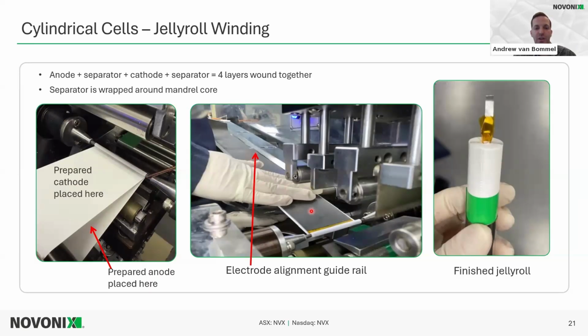This is just showing the cathode placed on the top with an electrode alignment guide shown there, so everything is aligned. Again, the same thing, the anode has an overhang of 1 millimeter on each side, and the separator further has another millimeter overhang on each side.